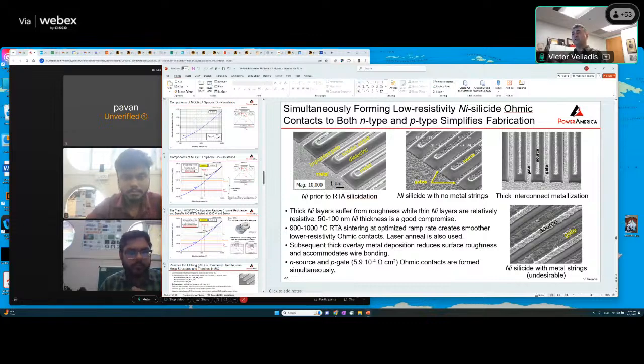So when you do that first nickel silicide, you only have metal on the front of the wafer, not the back, because remember, we want to thin the back of the wafer, we want to thin the substrate to reduce the resistance. So you do the front of the wafer along the process to form ohmic contacts in the front, and then at the very end, you put resist in the front, you flip the wafer over, and the resist is to protect the front surface, and you thin the substrate in the back.